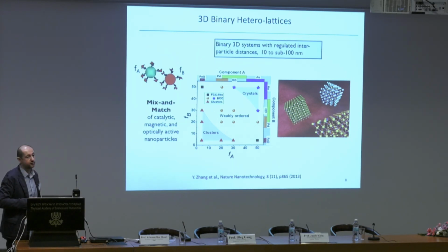Then for smaller numbers, it will be weakly ordered, and below 20, it will essentially be formation of clusters. And it just tells you that from a percolation point of view, 20 is a very big number. Why it's 20 just gives an indication that there is probably certain bundling of DNA between particles.